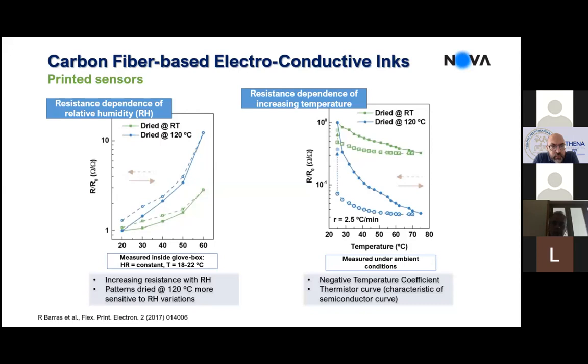So, and you are increasing the resistance with humidity. Okay, and of course, the more porous structure responds better to the humidity than the less porous structure. So you see, you can tune the sensitivity by controlling the drying process also of these patterns.